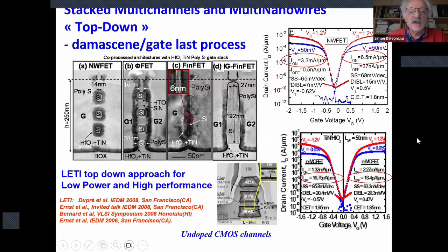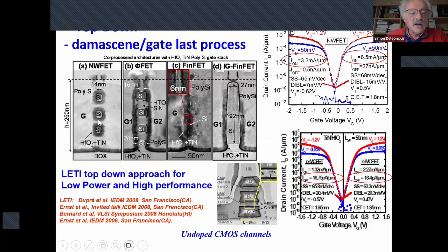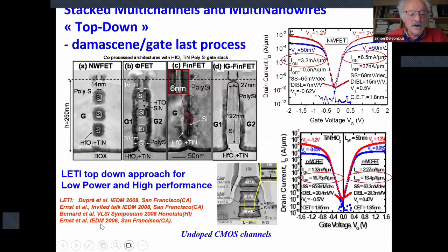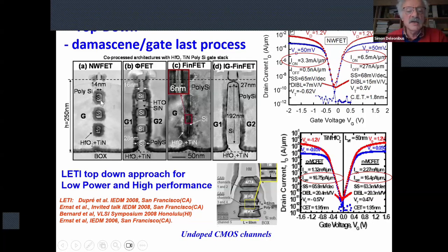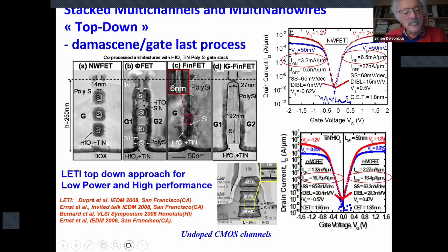Okay, so I talked about the ultimate scaling into nanowires. Here you can see how we, I would say, elegantly made these nanowires as early as 2006. Very recent publications by other authors at IEDM, other companies have shown this approach, and you can see that we were among the pioneers. So basically how do you do this? You just grow a superlattice of silicon, germanium, silicon, alternatively, and you could superimpose up to 20 of these epitaxially grown strained semiconductor layers. Then you remove silicon germanium very selectively to silicon, and you leave silicon.